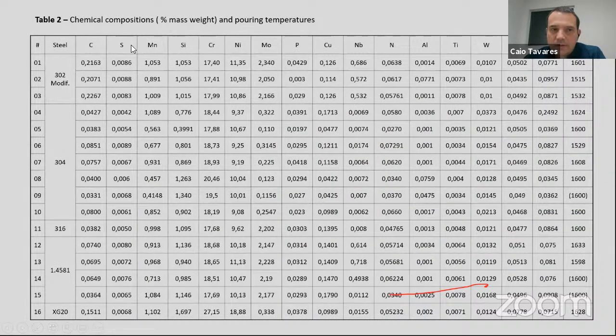And those are the chemical composition of the alloys that we cast. See, 16 different heats in different stainless steels. And here all the composition of this alloy that we got in the spectrometer. And those was the pouring temperature of those samples.